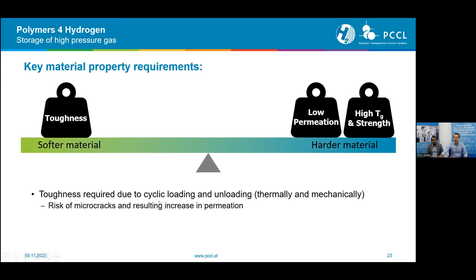filling of the tank, the pressure just changes all the time, and this induces a cyclic load to the pressure vessel. Also the temperature increases during the filling and unfilling, so that we have thermal and mechanical cyclic loads, and those could induce microcracks, which can of course also occur during the curing process. And as you can imagine, cracks in the matrix would result, of course, in an increased permeation.